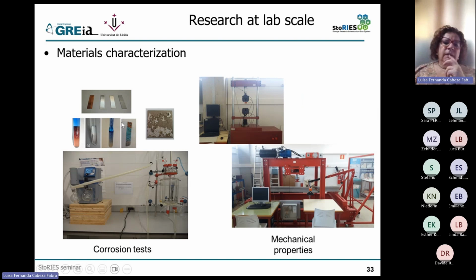We do a lot of corrosion testing. We do this by immersion testing. At the bottom, it's an example of a setup that we developed once that we wanted to do corrosion under vacuum conditions. Even though we think that there is no corrosion under vacuum conditions, there is, because in reality there is no perfect adiabatic system. So in reality, there is no perfect vacuum system. So you will always have some oxygen in there unless you use an inert gas. And we did some tests also under vacuum with this equipment, which was very interesting. And also we do mechanical properties at small scale and big scale, depending on what we are developing.